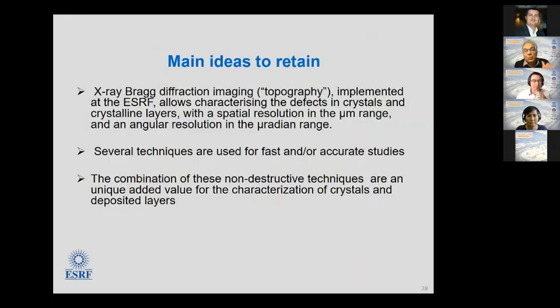So the main idea to retain is that X-ray Bragg diffraction imaging topography, which was implemented at the ESRF and especially at the BM05 beamline, allows characterizing the defects in crystals and crystalline layers with a spatial resolution in the micrometer range and an angular resolution in the microradian range. Several techniques are used for fast and/or accurate studies, and the combination of these non-destructive techniques is a unique added value for the characterization of crystals and deposited layers.